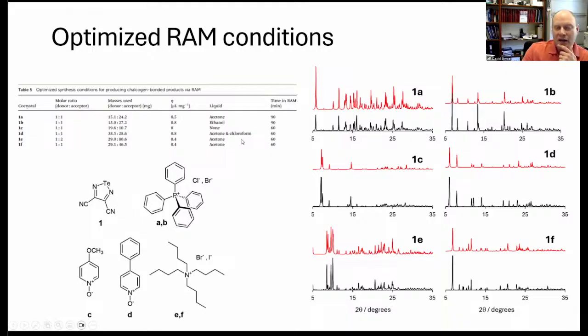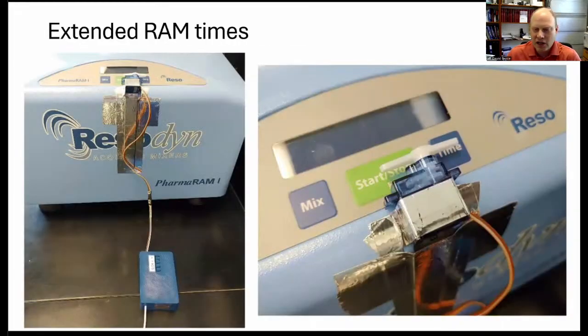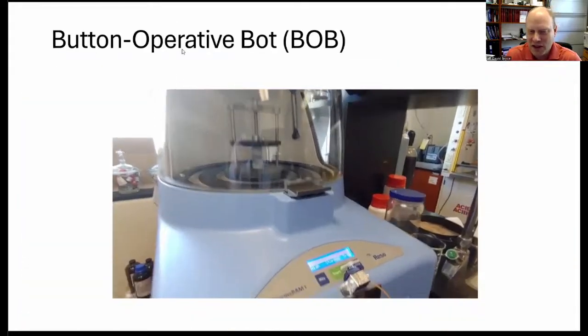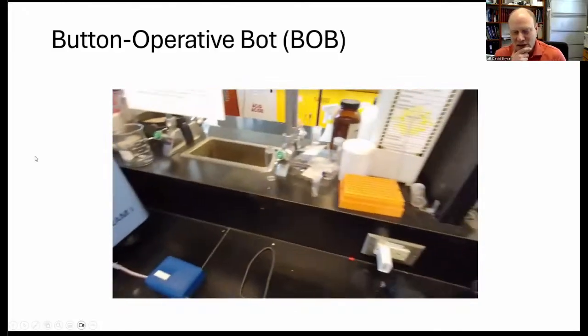And I'll point out here that the time in the RAM here was up to 90 minutes. So in the Pharma RAM 1 that we have, the firmware controls us to running up to 5 minutes only, which has been useful in many cases, but we found that much longer RAM times were necessary in this case. And so just as a little side project here, my student designed a little robot to basically push the button every 5 minutes and 1 second. I understand there's probably some commercial robots you could buy to do this, or I could buy a bigger Pharma RAM, but I thought this just was an interesting little tool that my student made.